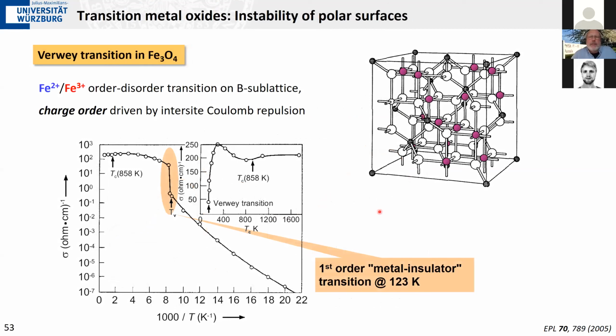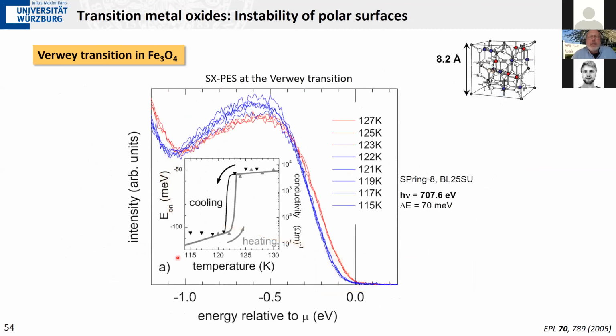That allows you then to also look at phenomena on a finer energy scale. For example, in magnetite, there is this famous Verwey transition at about 120 Kelvin, where you change from a nearly metallic to an insulating behavior. And that can be resolved as you go in very small temperature steps through this transition, and then you can see small changes in the onset of where the spectrum starts because of a small change in the gap. That's only possible if you go to these high energies.